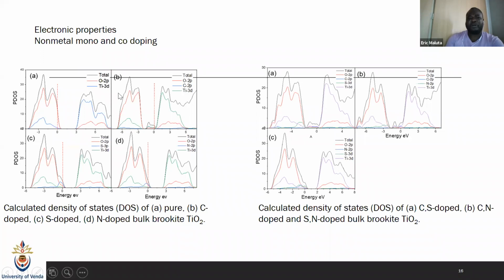And this we can see from monodoping and also co-doping, as indicated on my right-hand side where I'm moving the cursor, that the band gap is reduced. And when the band gap is reduced, we also have introduced new bands, either on the valence side or on the conduction side, which depends on the non-metal we're using or the metal we're using, whether we are including the bands on the conduction band side or on the valence band side, which is what we see from our results.